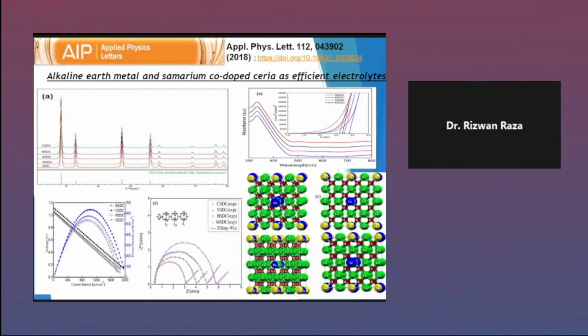Another work, because there are different materials, you can explore different things, but you have some benchmark and different parameters. So after that, another of my PhD students studied different alkaline earth metals as a co-dopant in the ceria, and found different behavior. It is more stable, and the conductivity is also increased. And here are a few results: barium based, calcium and some strontium based. They have different behavior, and you can see barium has a better performance at low temperature. And also in the impedance spectroscopy, ionic behavior is there, and there are spikes there, which is also confirmation of some electronic behavior in that particular material.